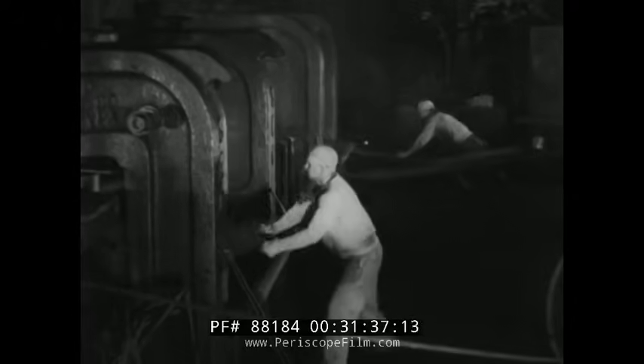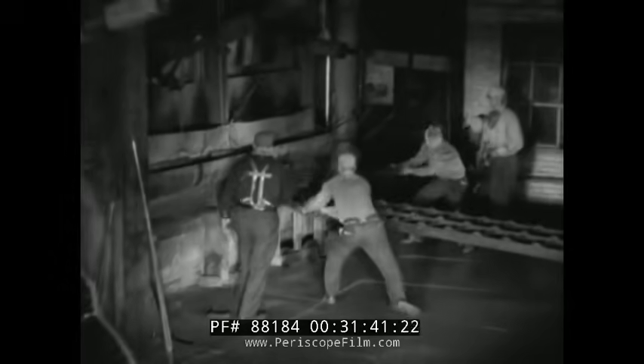With each pass, pressure is added to the rolls to reduce the thickness and increase the length of the sheets. When the hot rolling has reached a certain point, the sheets are taken to what is known as the finish reheat furnace. In this furnace, the non-oxidizing atmosphere is controlled to hold the carbon monoxide content to a very close limit. When the sheets are removed from the finish reheat furnace, the final hot rolling is carried out.